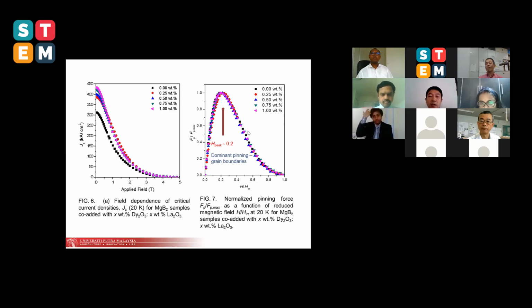In order to assess what kind of pinning mechanism is in the sample, we plot the so-called flux pinning force over the reduced applied field. The peak here has a value of about 0.2. Looking at the pinning mechanism, a peak value of 0.2 corresponds to grain boundary pinning as the dominant pinning mechanism in the sample. And this is consistent with the decrease of the average grain size of our samples.